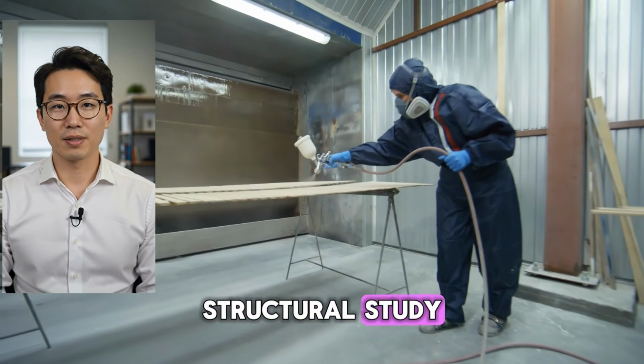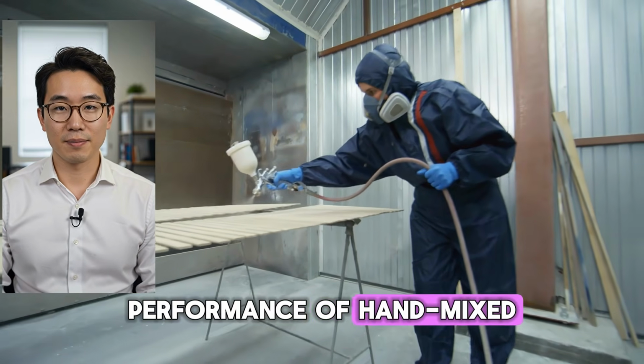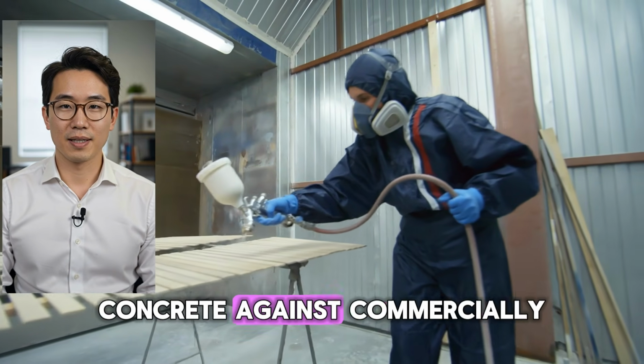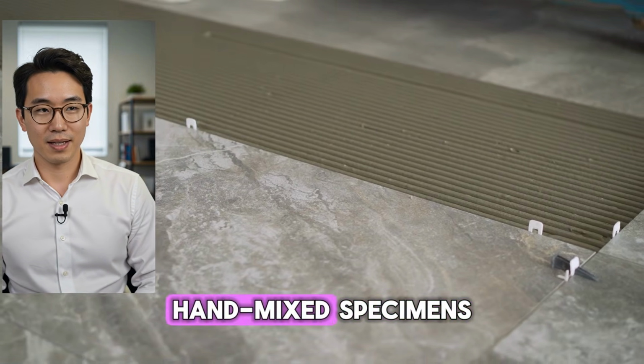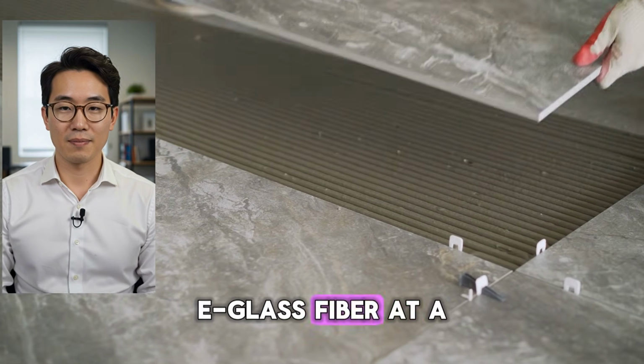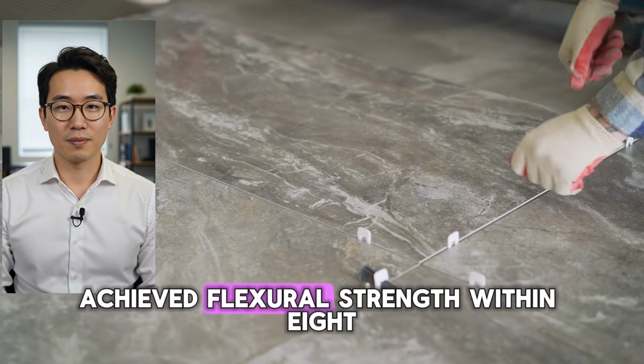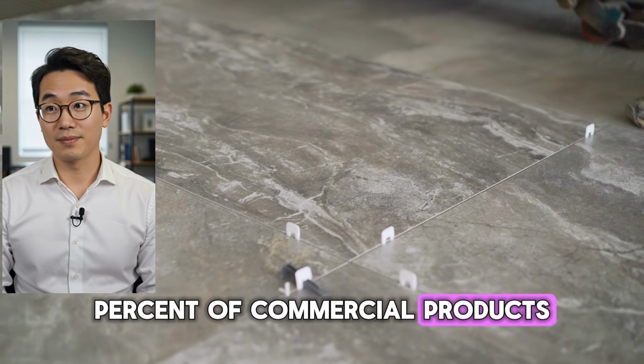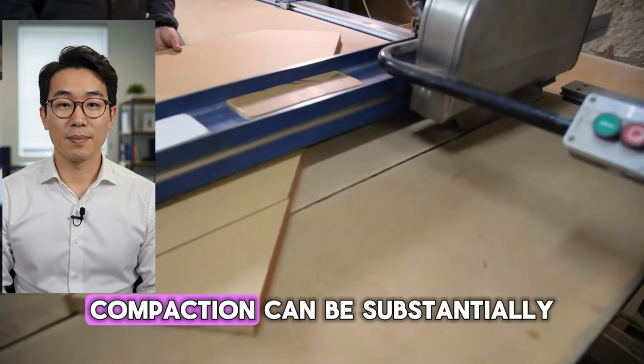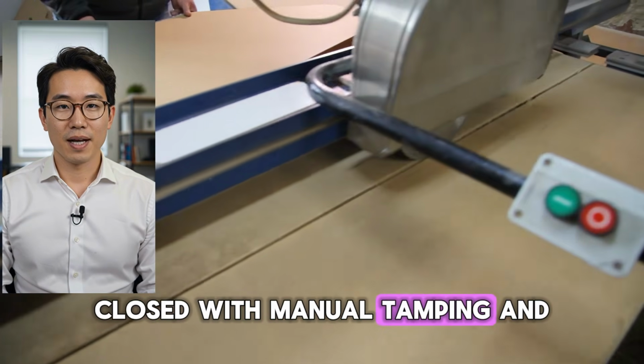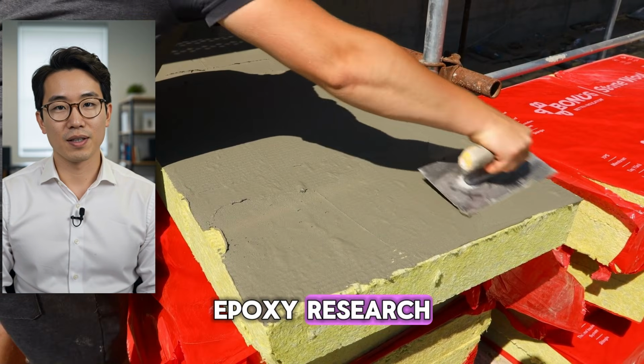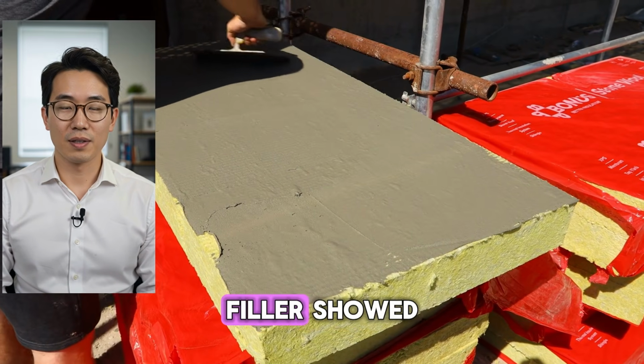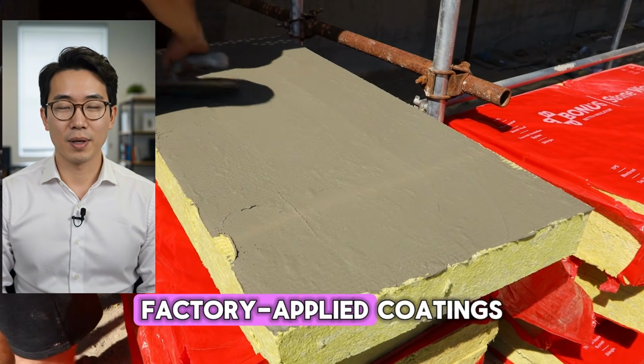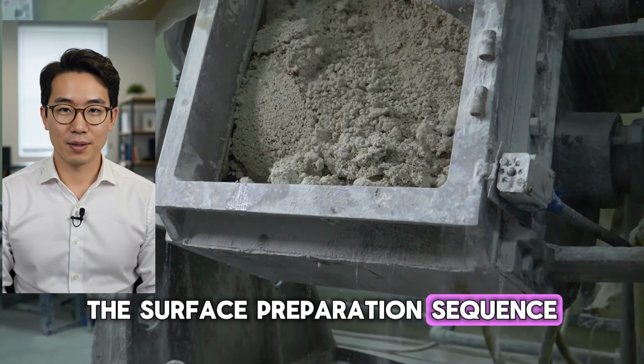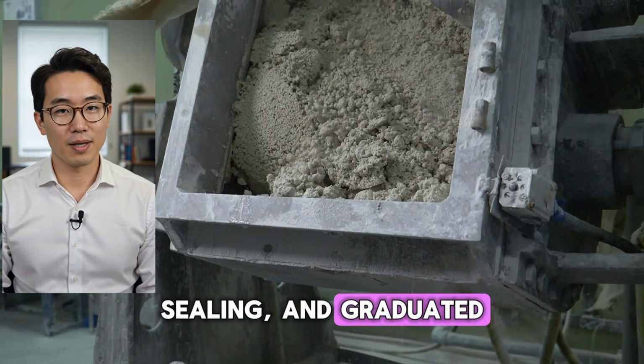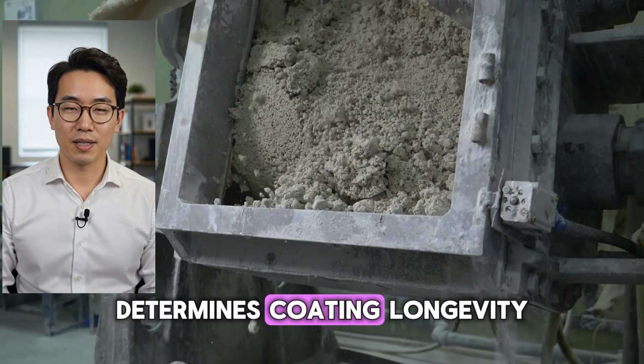A 2019 structural study measured the mechanical performance of hand-mixed glass fiber reinforced concrete against commercially produced GFRC panels. Hand-mixed specimens, using standard chopped E-glass fiber at a 3% ratio, achieved flexural strength within 8% of commercial products. The industrial advantage of vibration table compaction can be substantially closed with manual tamping and extended wet curing. Epoxy research confirmed that concrete substrates sealed with acrylic filler showed adhesion values exceeding factory-applied coatings. The surface preparation sequence, mechanical abrasion, sealing, and graduated sanding, is the variable that determines coating longevity.